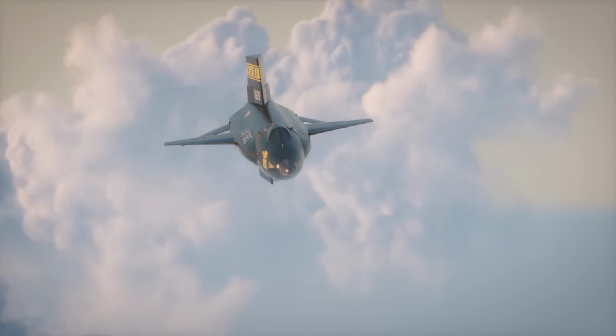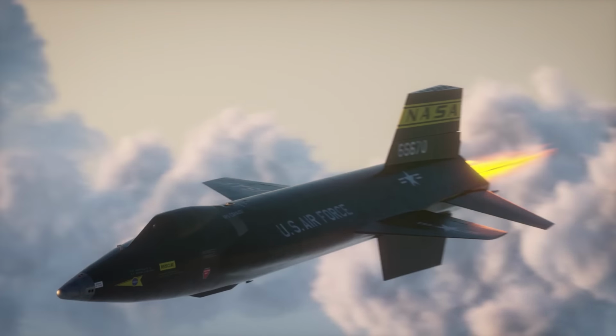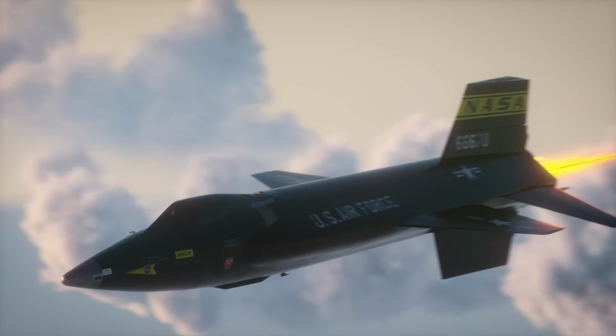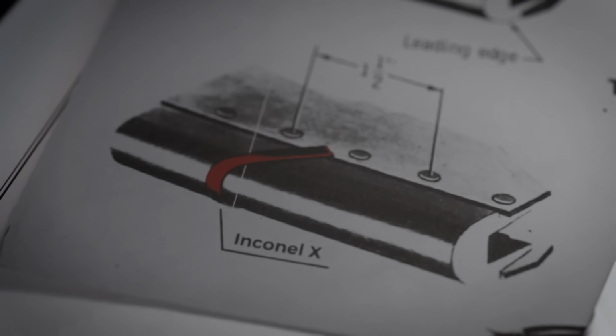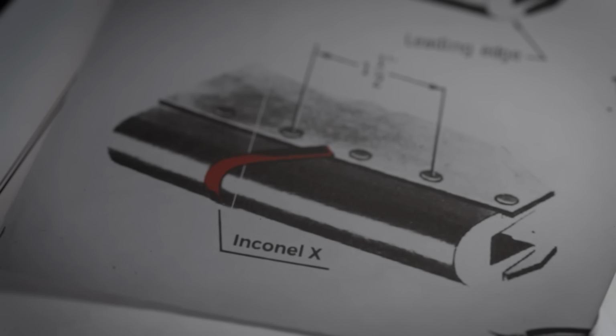To investigate the heat of hypersonic flight, the X-15 was painted with a special kind of paint that reacted to heat. And after one flight, the X-15 returned with strange, wedge-shaped patterns emanating from the leading edge expansion joints, small gaps in the leading edge to allow the Inconel skin to bend and contort with the wing without buckling. This localized heating was happening as a result of turbulent flow, increasing the rate of heat transfer to the metallic skin of the aircraft. To fix this, small floating strips of Inconel were placed over the expansion gaps.